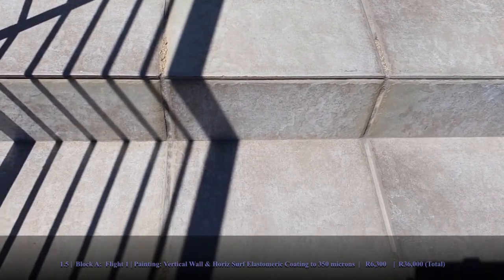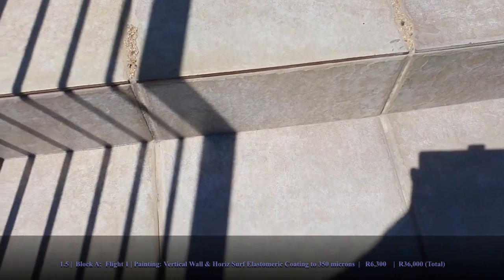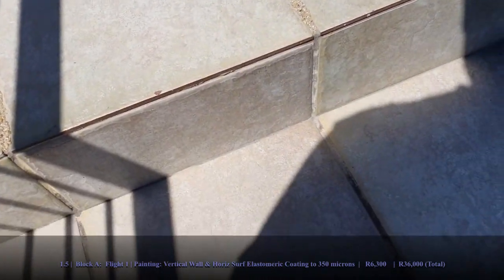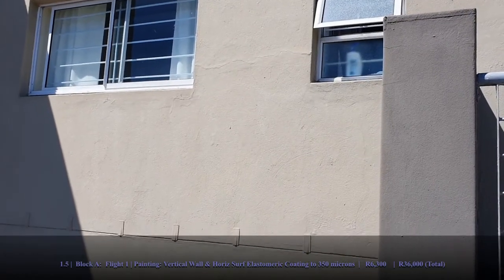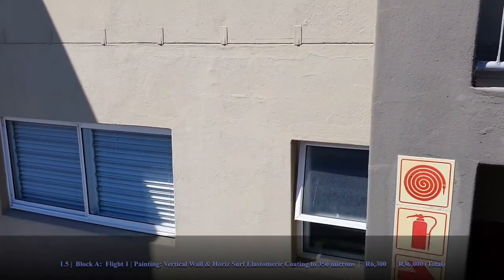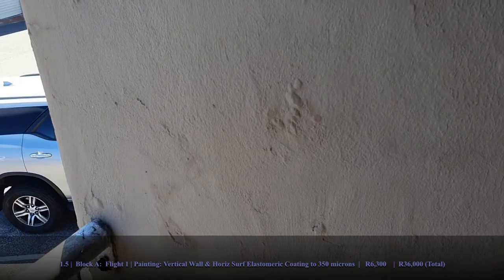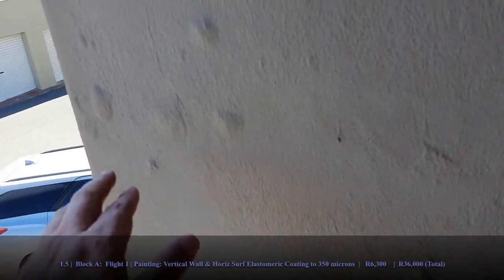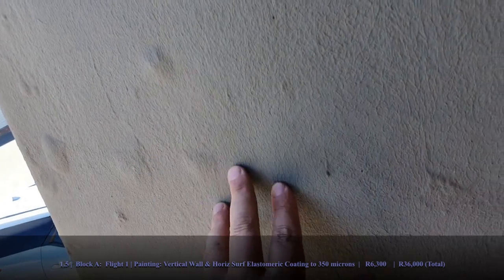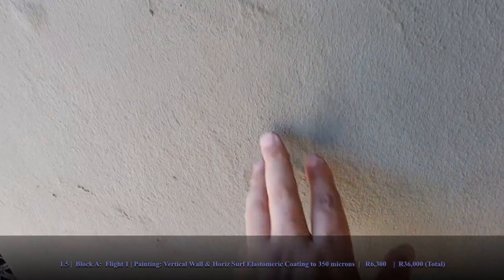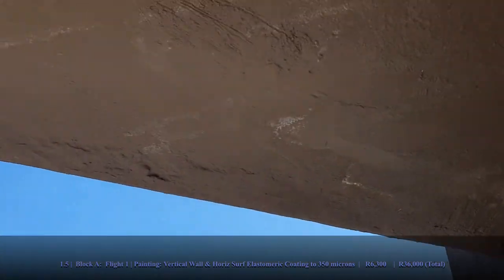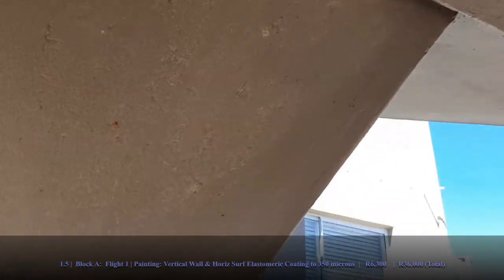Some attempt has been made to try and waterproof the grout, but this is also obviously failing. There are some cracks which are starting to show again on the main building. You can see that the paint coating hasn't failed because although water has tried to escape, what's happened is the paint has let it escape, but it hasn't delaminated. It's gone back, so it would have bubbled during winter and then contracted again, and that means that it's really doing its job. But there's a lot of water that's coming in from the balconies above, and so if it was any other coating it probably would have broken by now.